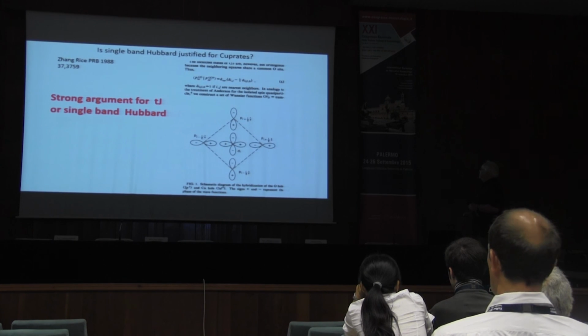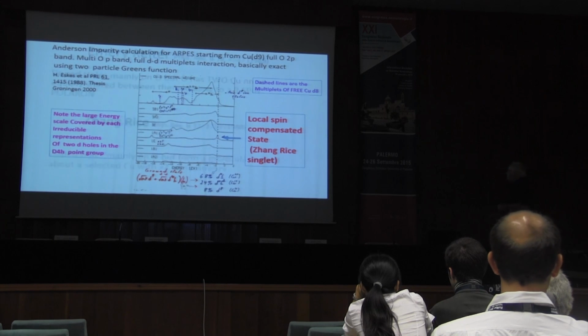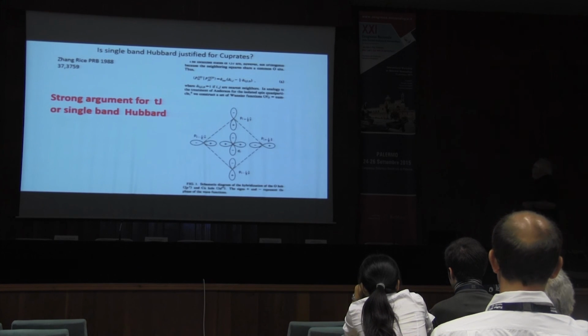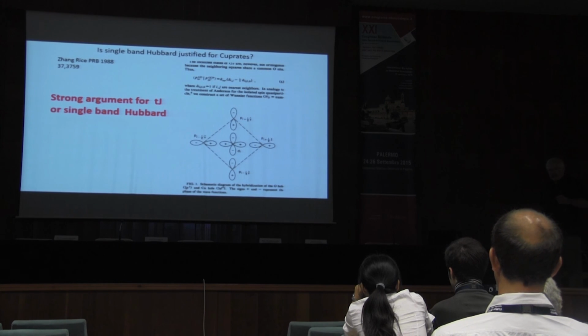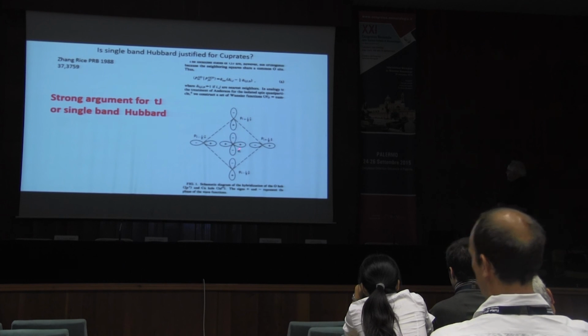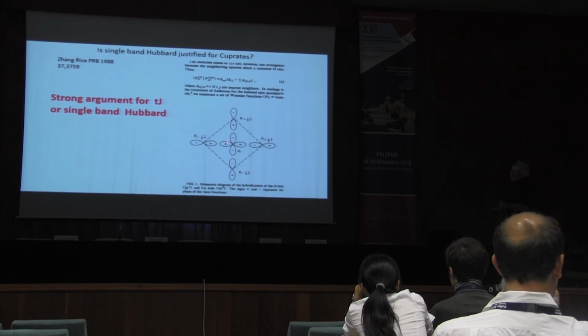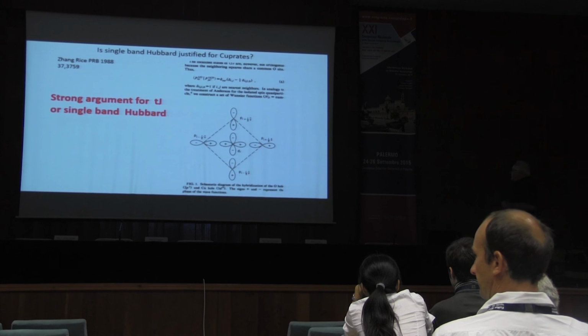I'm still not getting there. With a very strong exchange interaction between the copper and the oxygen. That exchange interaction is more than half an electron volt. It's huge. So the story then was that you would form these singlet states with a hole in this linear combination of atomic orbitals that have x squared minus y squared symmetry exchanging with this electron in an x squared minus y squared orbital and forming a singlet state.